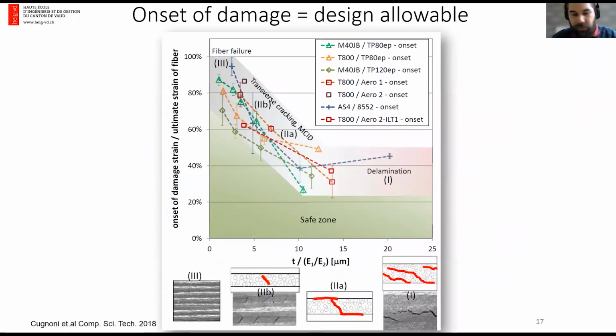We've collected all these results in an empirical, let's say, damage failure map or design allowable map, where you have here on the vertical axis the onset of damage strain, so the strain at onset of damage normalized by the ultimate strain of the fiber. So we have here different types of fibers, so that's why we had to normalize. And on the horizontal axis, the ply thickness normalized by the anisotropy of the ply. Actually, it was found that the anisotropy of the composite is important. So for higher modulus fiber or lower modulus fiber, there's a small effect also.